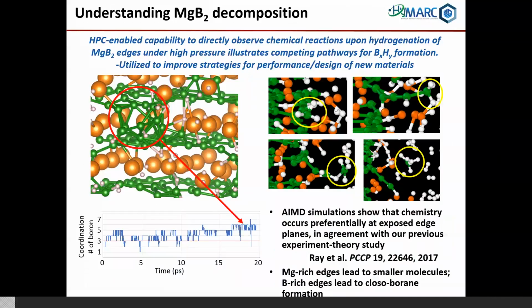And what we learned, in short, is that there are different, essentially defect sites in this material, basal planes where there may be magnesium or boron exposed, and the reaction of hydrogen with those sites has different activation energies. That's what's shown down here in this lower left-hand corner. And essentially what we see is that the activation energy evolves with the extent of decomposition of the material.